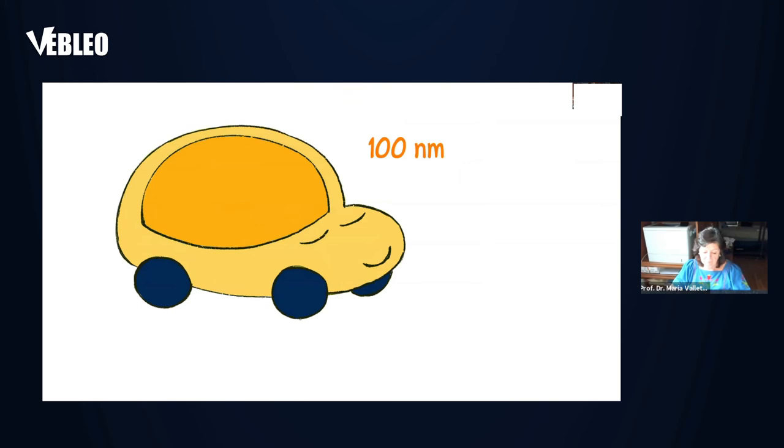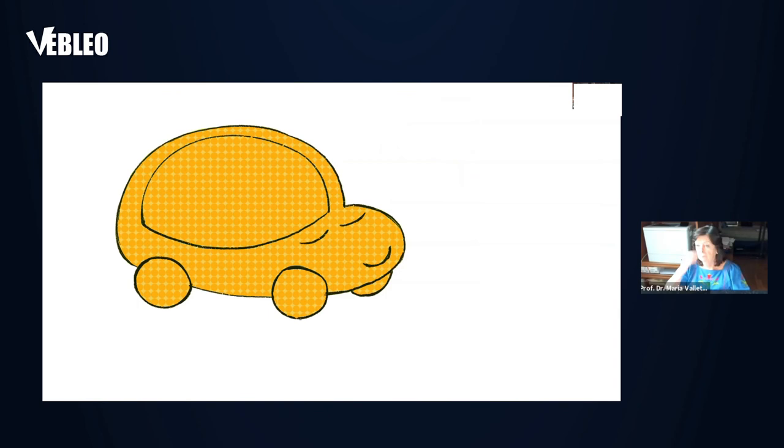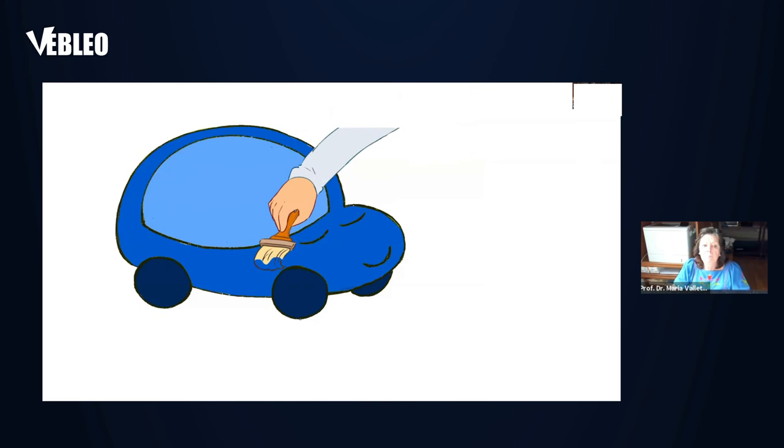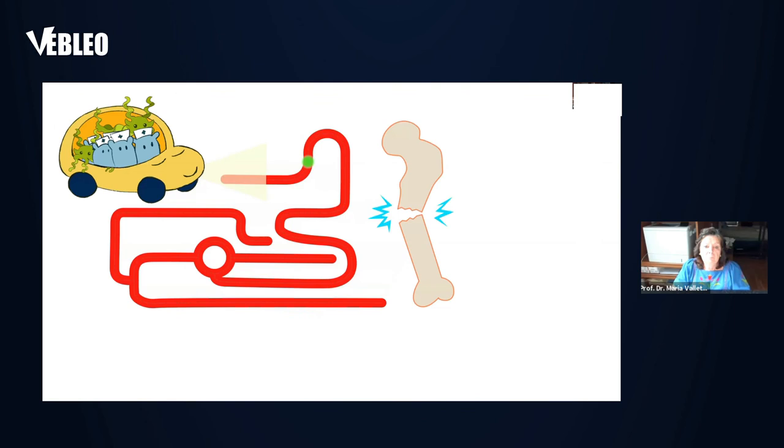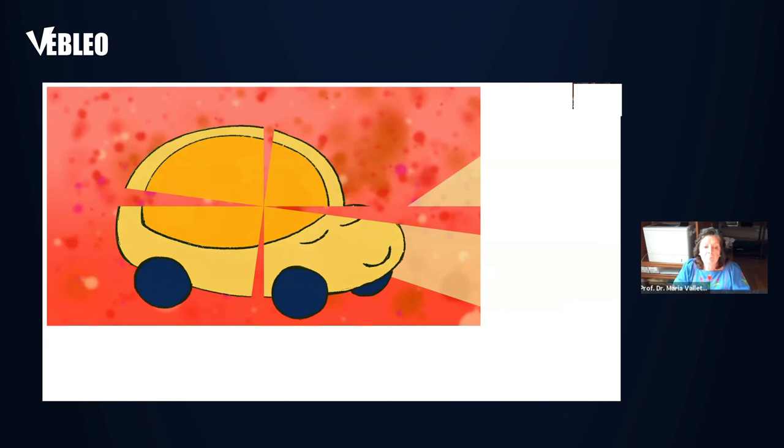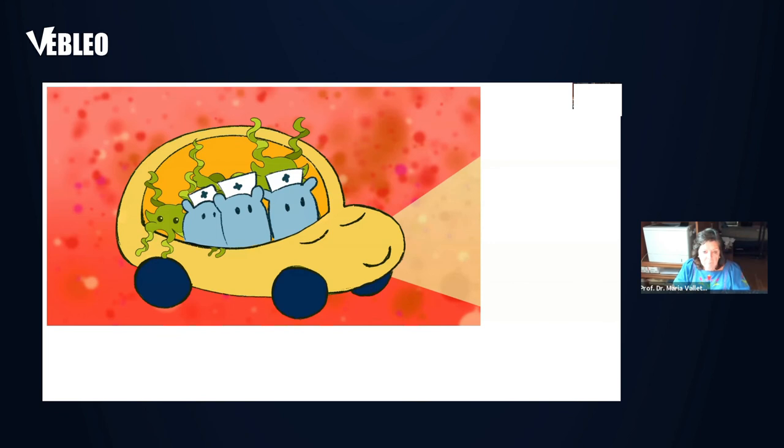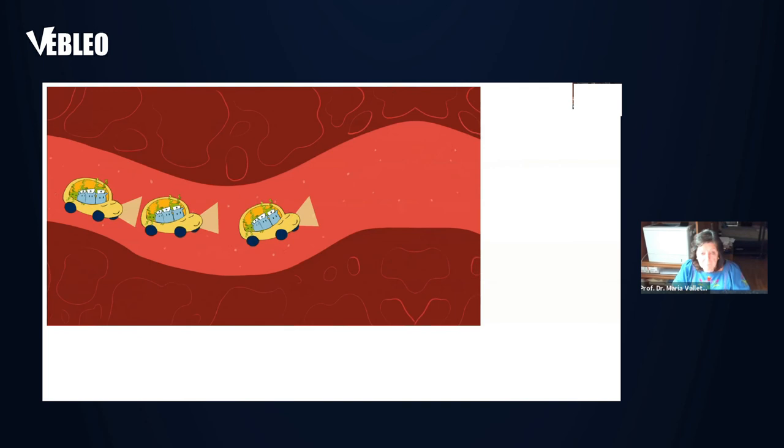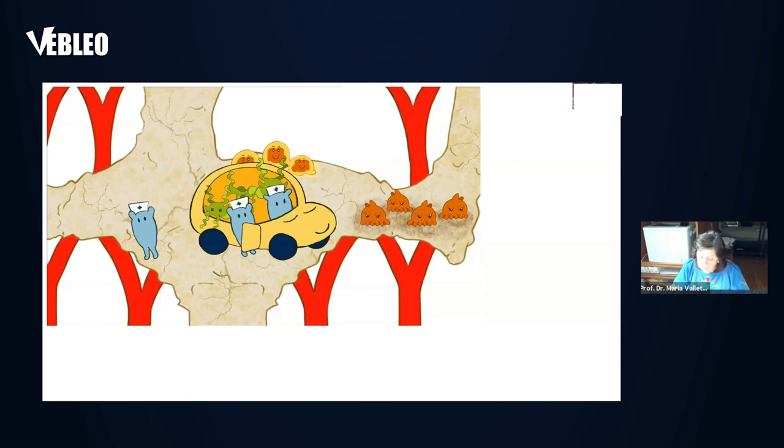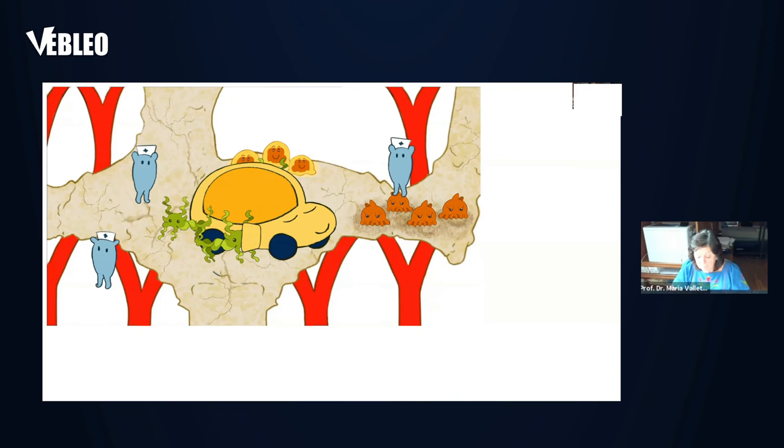These nanoparticles measure around 100 nanometers and present a huge amount of pores. Moreover, their surface could be modified with different polymers and molecules to provide them with different capabilities: one, protecting and delivering siRNAs; two, guiding the nanoparticles to the osteoporotic bone; and three, making them invisible for the immune system. We can also take advantage of the high loading capacity of the nanoparticles to load the pores with a large amount of osteostatin, an osteogenic peptide which stimulates bone formation and reduces bone resorption. In this sense, we can address osteoporosis treatment by simultaneously increasing the formation of new bone and inhibiting bone resorption, reaching higher levels of efficacy.